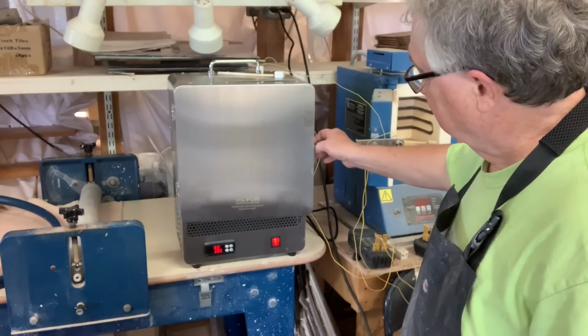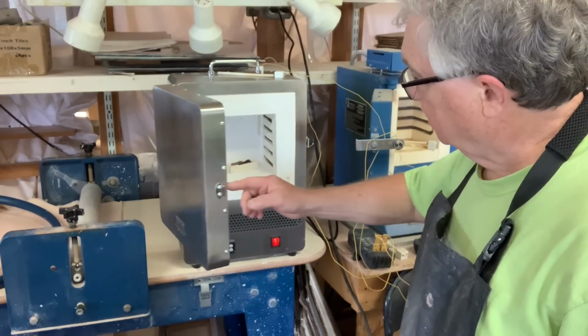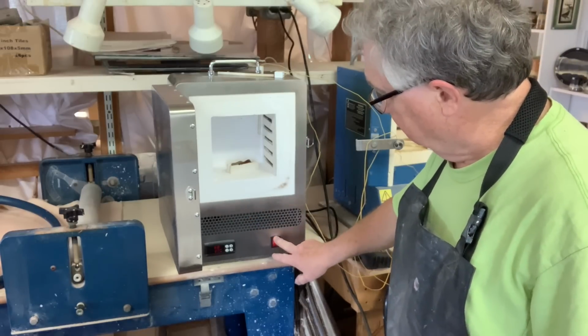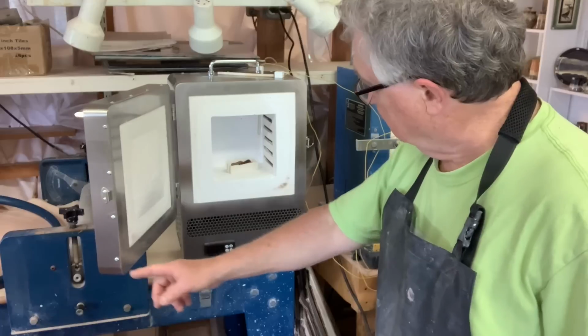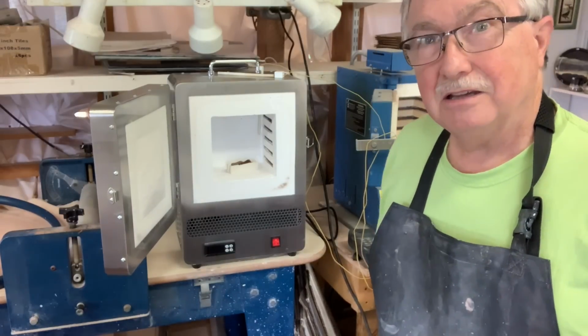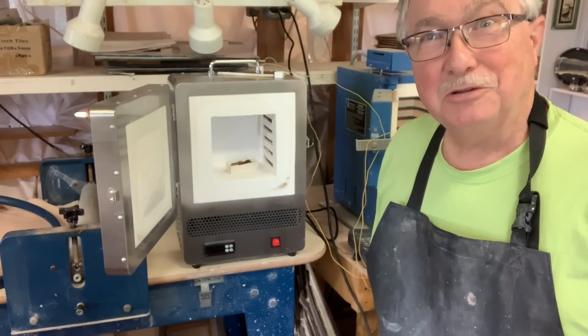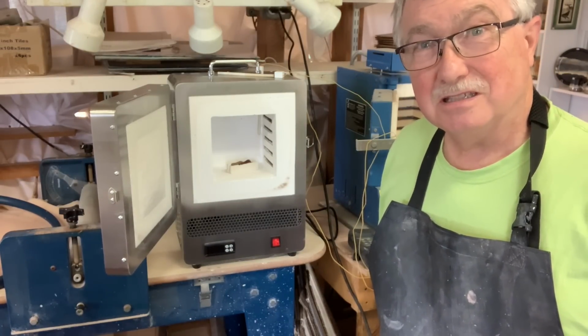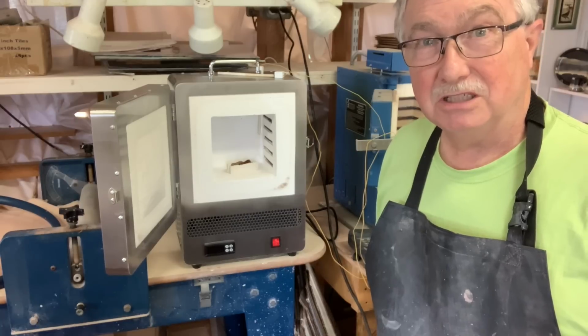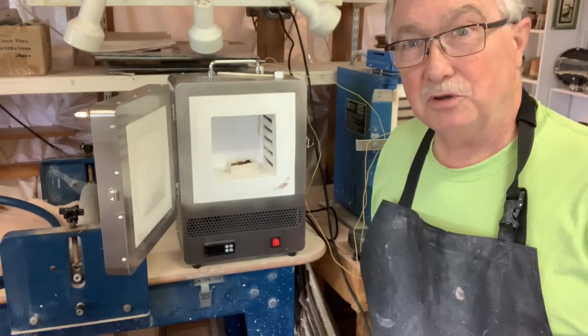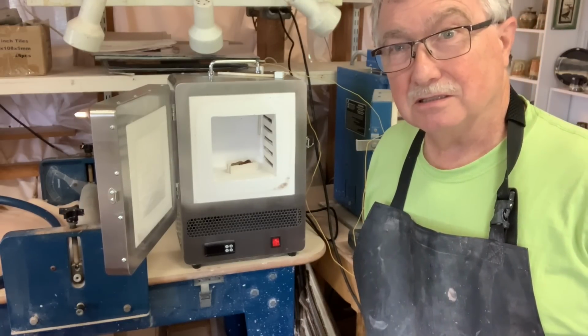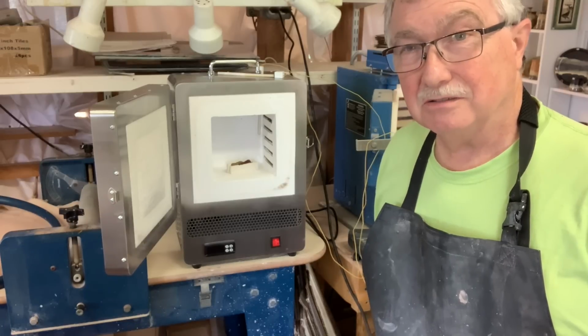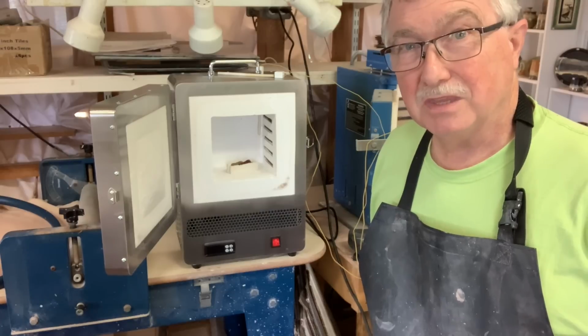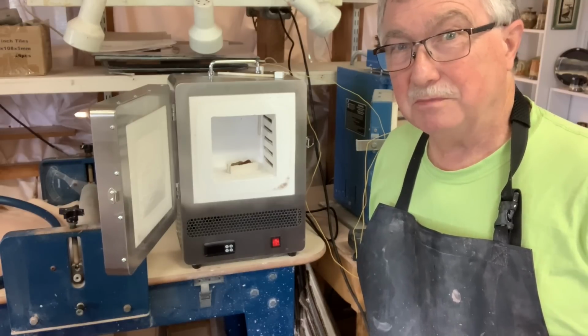So I uncracked it. Let's turn it off just to be sure. And it's good news and bad news. Good news is this sucker can get up to temperature really easily. So you have no problem reaching cone 6, I would guess, in this kiln, because it got to bisque temperature in, I don't know, 45 minutes, whatever it was.